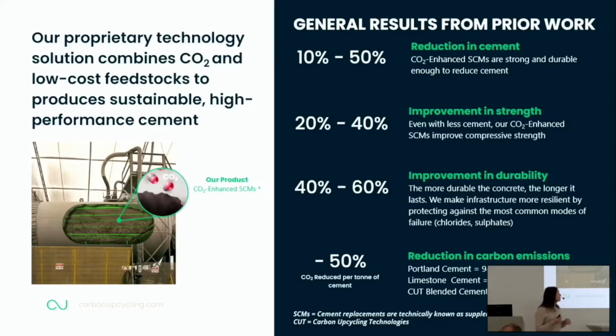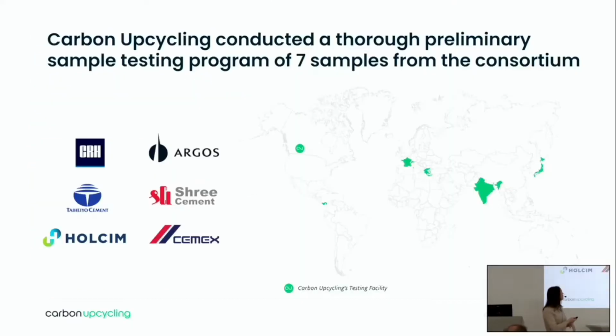We've been able to do 10 to 50% in cement reductions in ready-mix concrete. We are looking at improvements in strength, averaging between 20 and 40%. And we also improved the durability, which is another aspect of that longer-term deep decarbonization that we're looking at within the industry. And then, as a result of all of that, reducing cement, improving durability, we've been able to quantify about a 50% reduction in carbon emissions if we were to be at full scale.